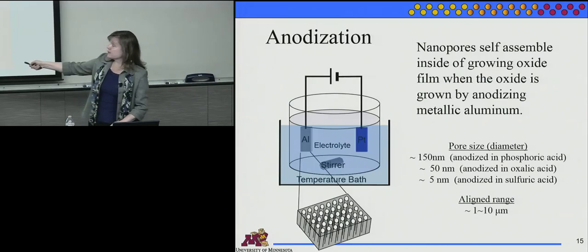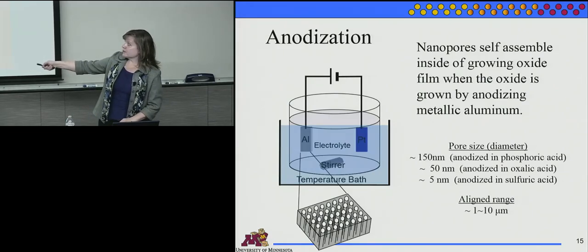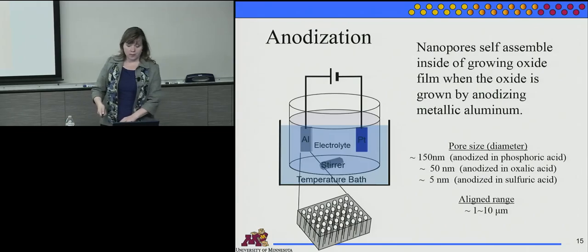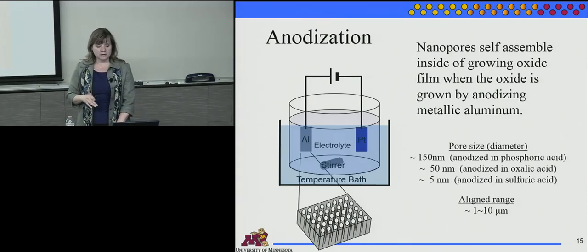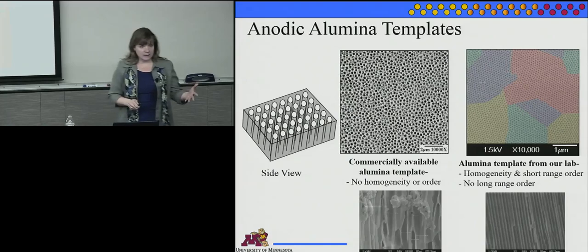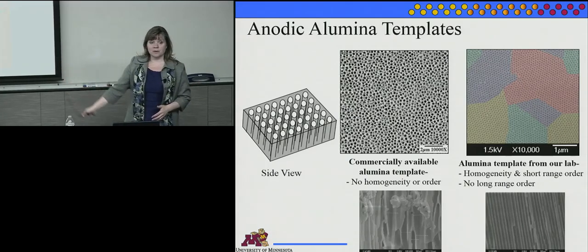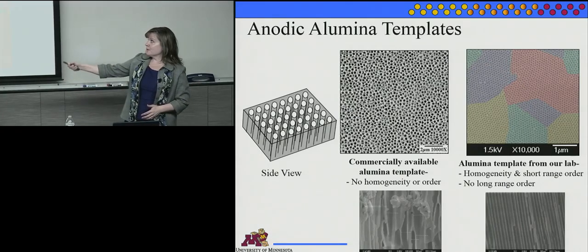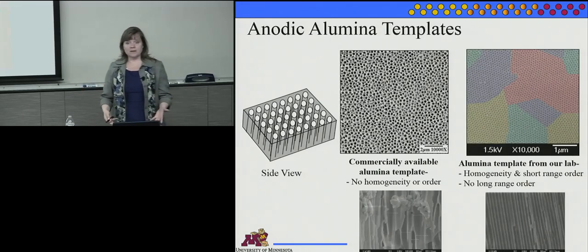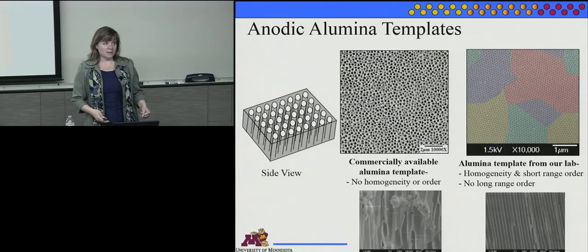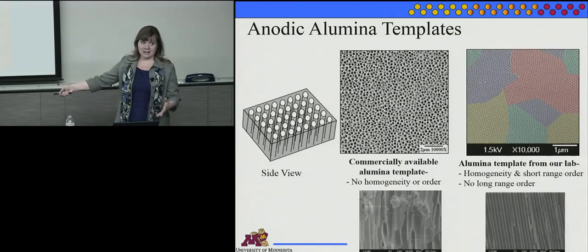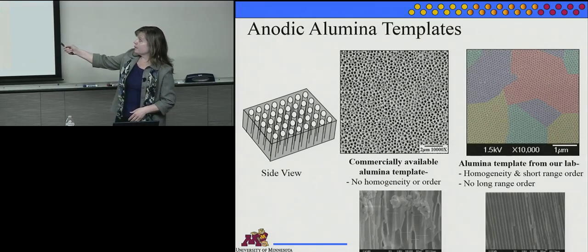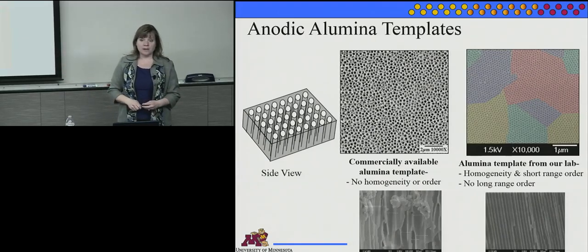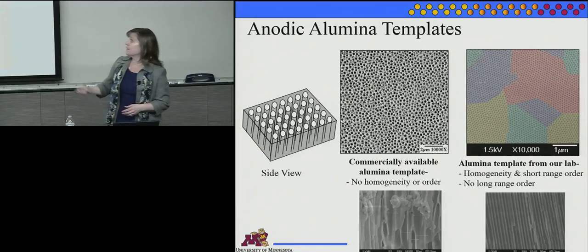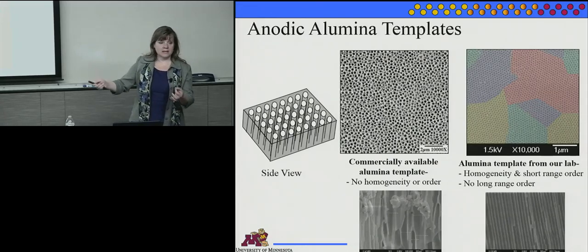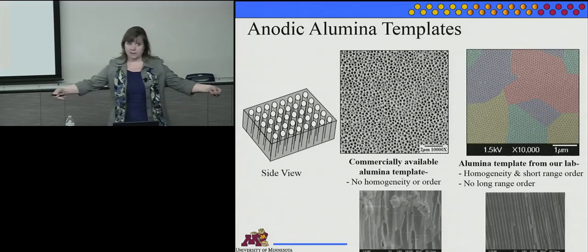We need a counter electrode. Depending on the voltage, the electrolyte, and the temperature, you can get a range of different pores out of this. And they self-assemble naturally. But if you're buying them commercially, you might end up getting something that looks more like this. So just be careful, because if you're buying just a filter, like a Whatman filter, they're not designed to be templates for nanowires. And you might find that you're not really getting a nanowire at all when you grow in these materials. But if you make your own, or there's some companies that are getting better at selling higher quality templates, you can see all of these have the same diameter anyway, even if they're not in a perfect line for a very long range.